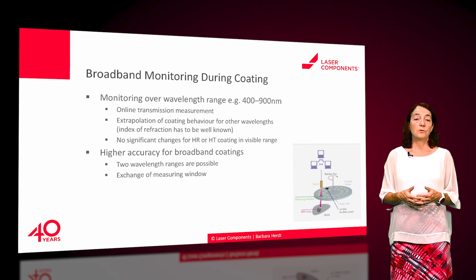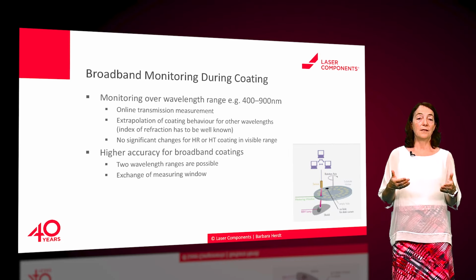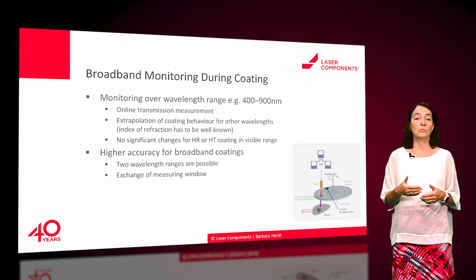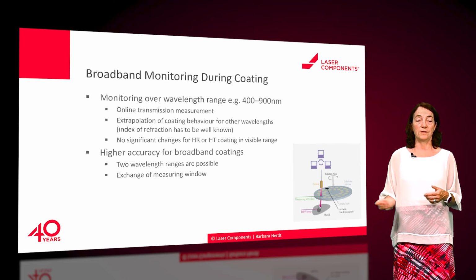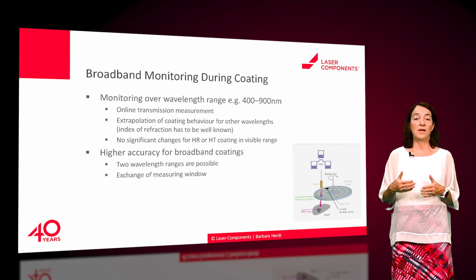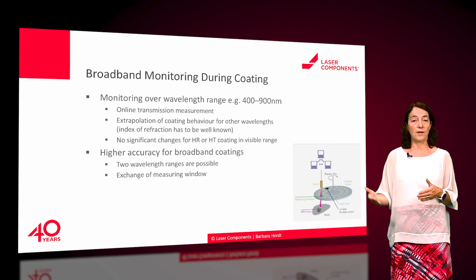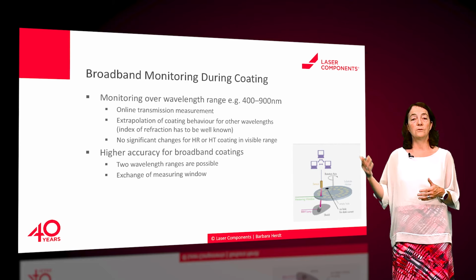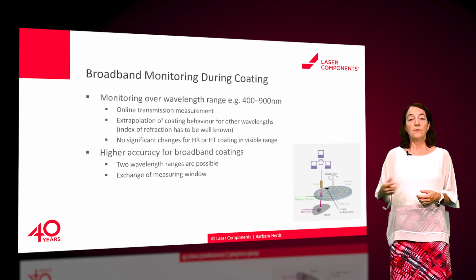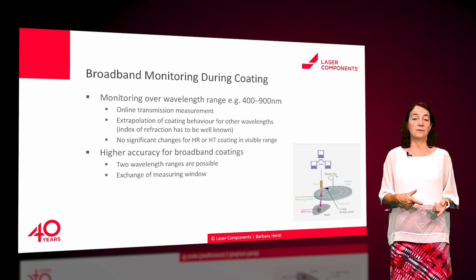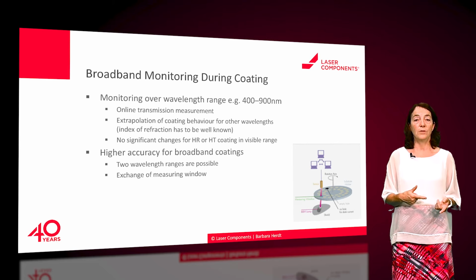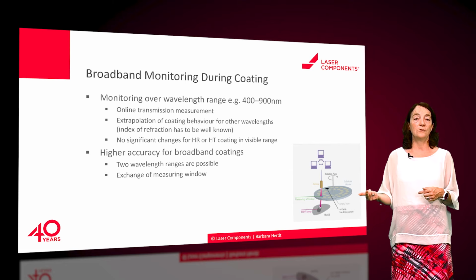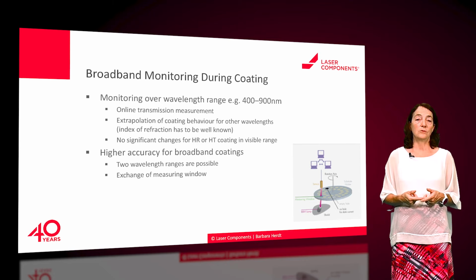Broadband monitoring means, like a monochromator, that the spectral behavior of a test glass is monitored during the coating process. In this case, the measurement is done over a large wavelength range, for example, over 400 to 900 nanometer. Even if the coating again is not designed in this region of 400 to 900 nanometer, the coating will be extrapolated to the monitoring wavelength range. What is important for all these extrapolations is the index of refraction over the complete wavelength range used.